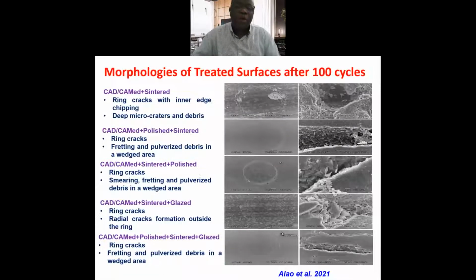Now, after 100 cycles, you see the damage is more heavy now. You can see the ring cracks with inner edge chipping, and also micro craters and debris. You can see the holes that are called micro craters. For the CAD-CAM polished sintered process, you see the ring cracks. You can see the fretting and pulverized debris in the wedged area.